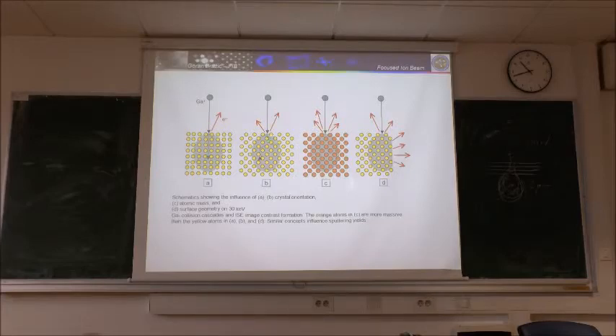If you have some other orientation, it is enough just to tilt your sample, your crystal, by 45 degrees. In one case you have channeling, depending on the structure, of course, and on the tilt of your sample. For instance, this one here, you have no channeling. That means that most of the gallium ions interact with matter, and there is a lot more signal, of secondary ions or secondary electrons. It's also important the Z,